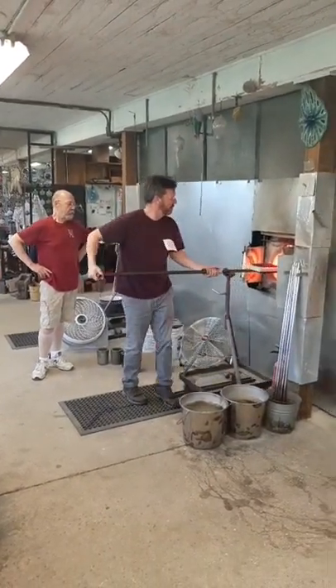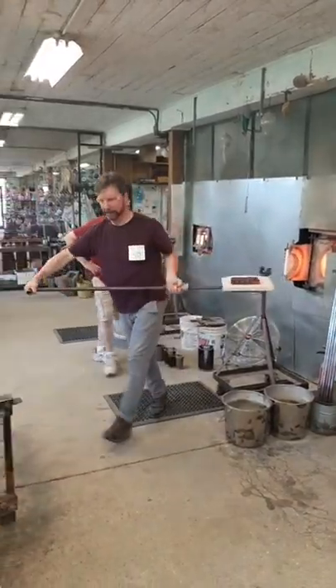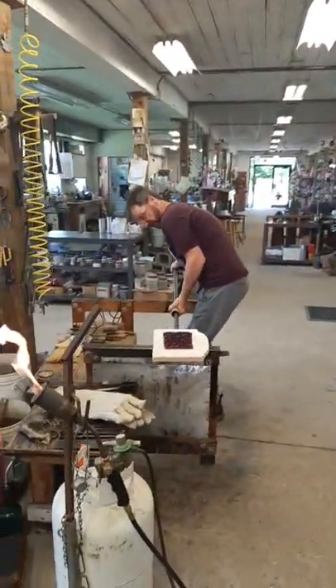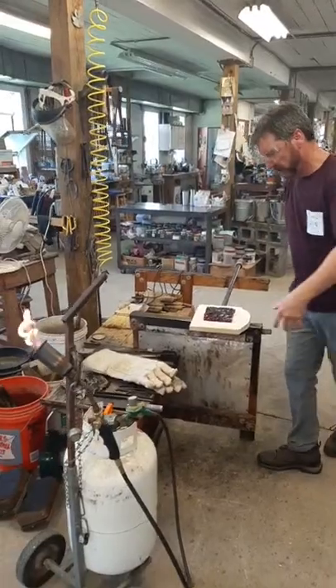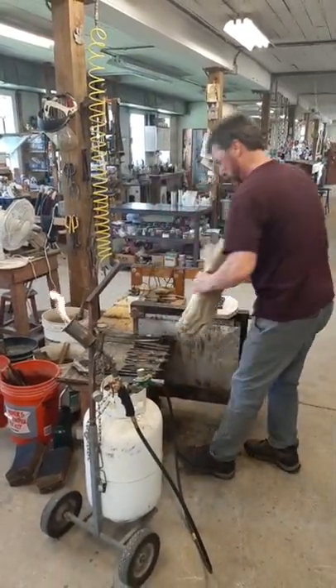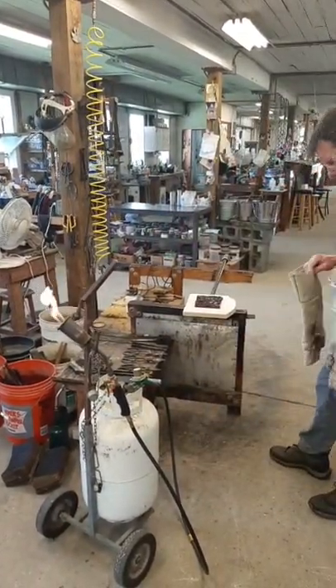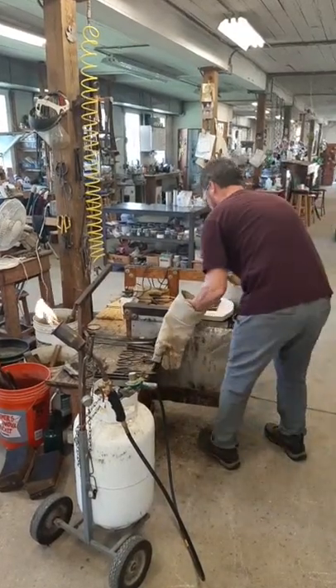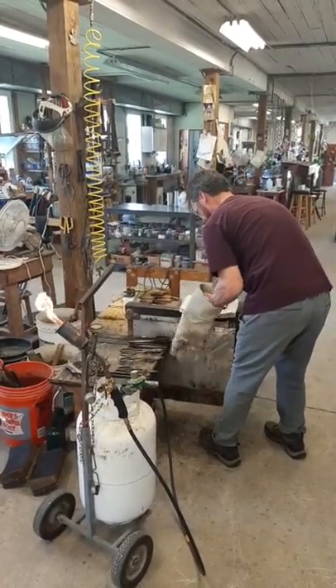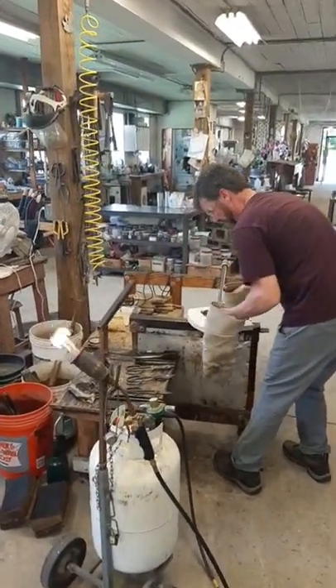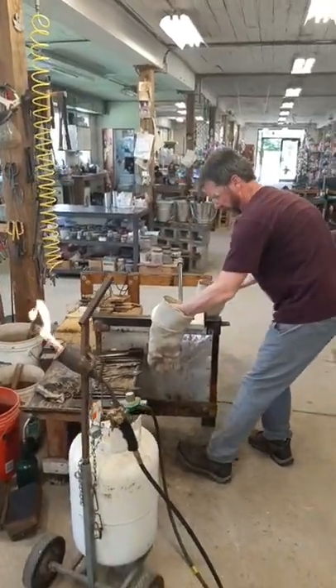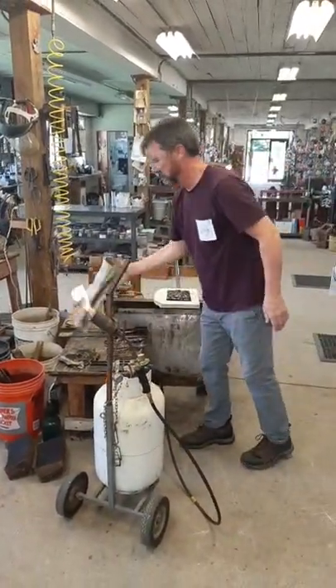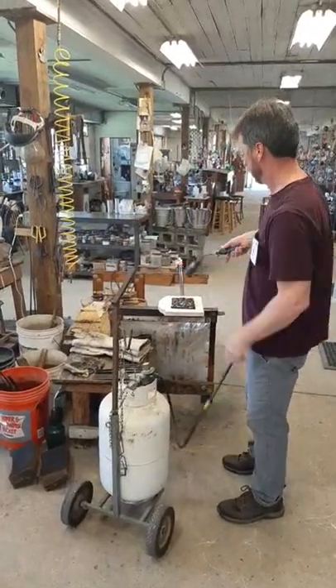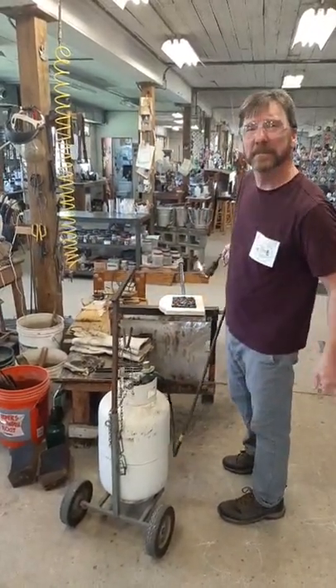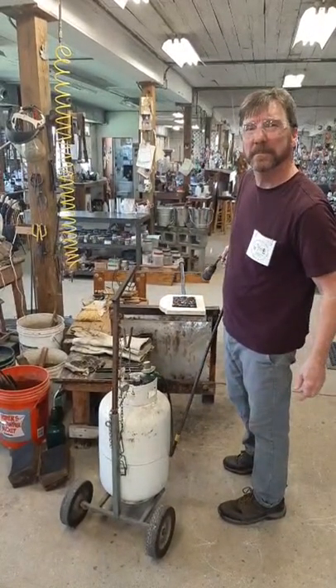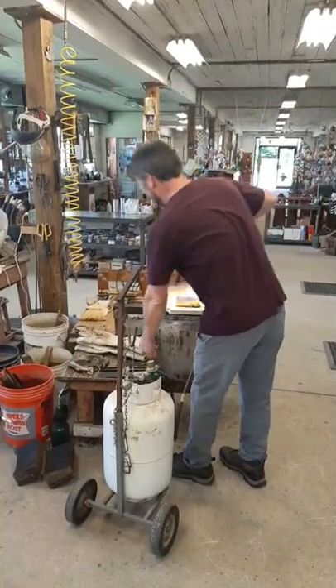So this is going to take a few minutes because he's going to bring this back and he'll be rotating the plate. So by putting on the gloves, he can turn the plate 180 degrees. The reason for this is we have the burner on one side of the glory hole and we want an even heat throughout this glass. Also, the middle does not get as hot, so he's going to torch it. Torch! Torch!